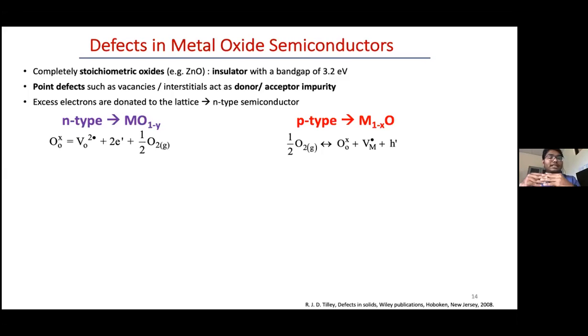So now in this case, what can happen? Either the metal can be missing or the oxygen can be missing. In both these cases, this would lead to different electronic scenarios. First of all, we can take an example where the oxygen is possibly missing. If the oxygen from an oxygen site leaves, you have a vacancy at an oxygen site. Effectively, the crystal cannot be charge deficient or charge excess. Overall, it is charge neutral.